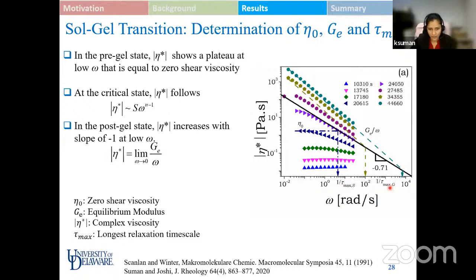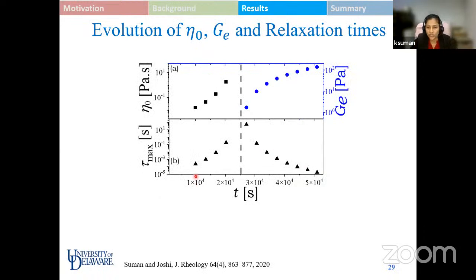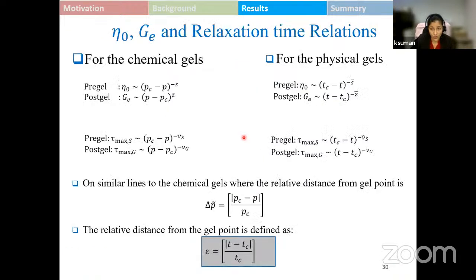So having quantified these 4 parameters, we plot them as a function of different times during the sol-gel transition. The dashed line over here is the point of critical gel transition. What was proposed in the literature was for chemical gels, and it was proposed to follow a power law scaling in the pre-gel and in the post-gel region with respect to the extent of chemical cross-linking. Now, we have a physical gel in hand, and the extent of cross-linking can be interpreted in terms of time of transition, because laponite dispersion is known to undergo spontaneous transition, which means that with increase in time, it undergoes transition. So we proposed replacing the chemical extent of cross-linking with time in these samples, and we write these scaling laws in terms of time over here.